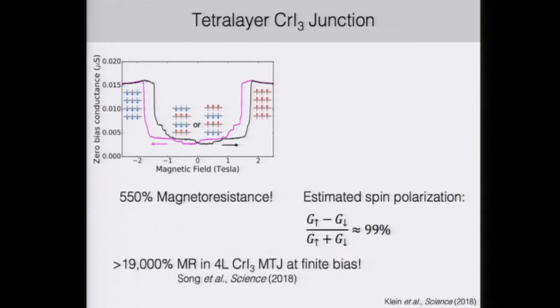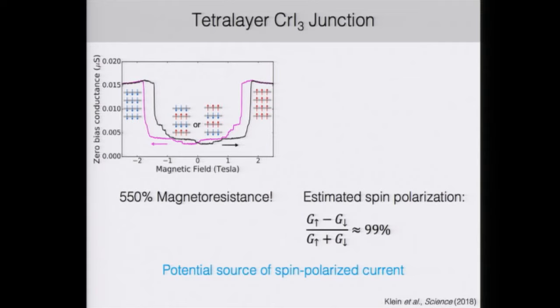And our collaborators in Xiaodong Xu's group actually observed that at finite bias, you can get very, very large magnetoresistance in 4-layer magnetic tunnel junctions of up to 19,000%. So these simple magnetic tunnel junctions using chromium iodide could potentially be used as a source of on-chip spin polarized current, which could be of interest to the spintronics community.